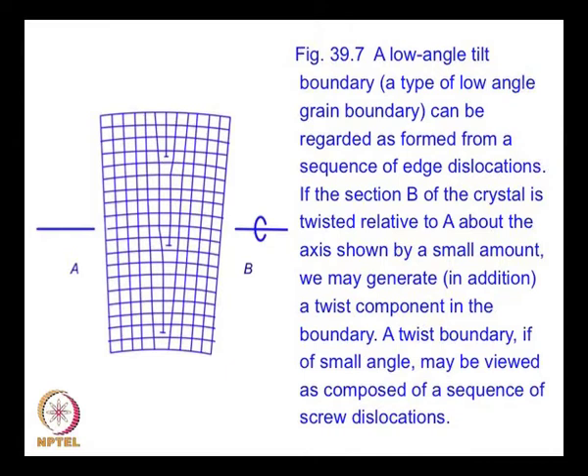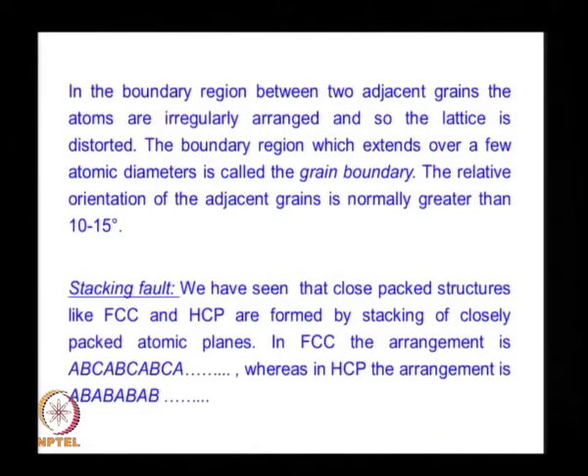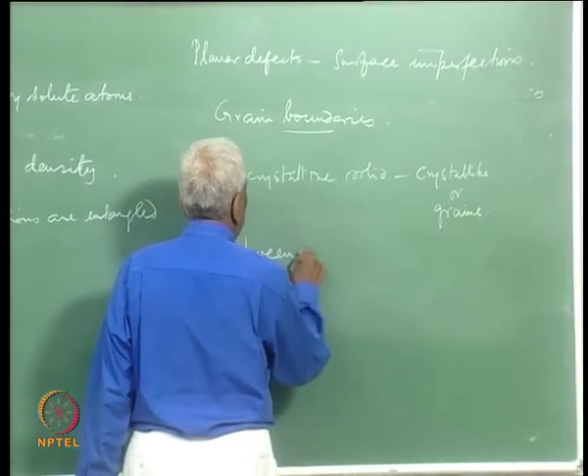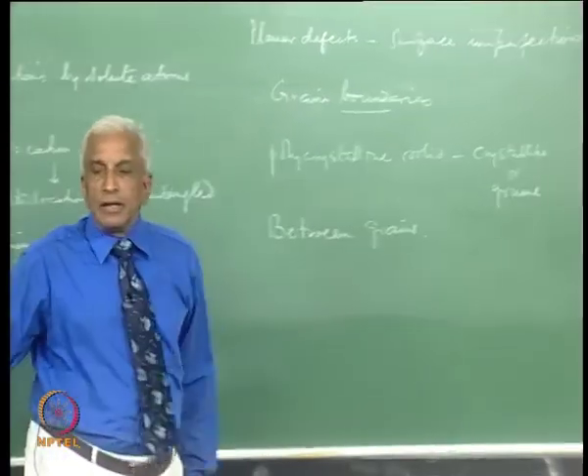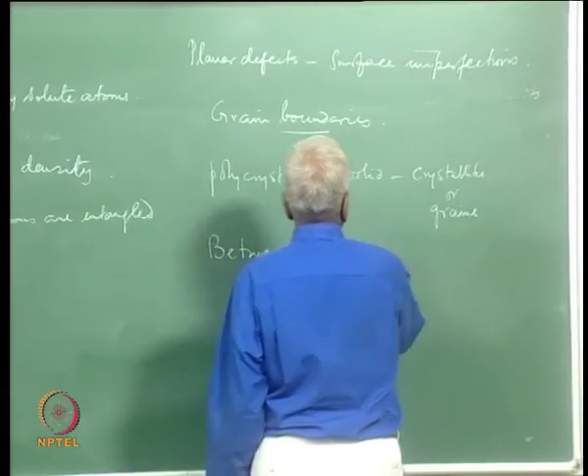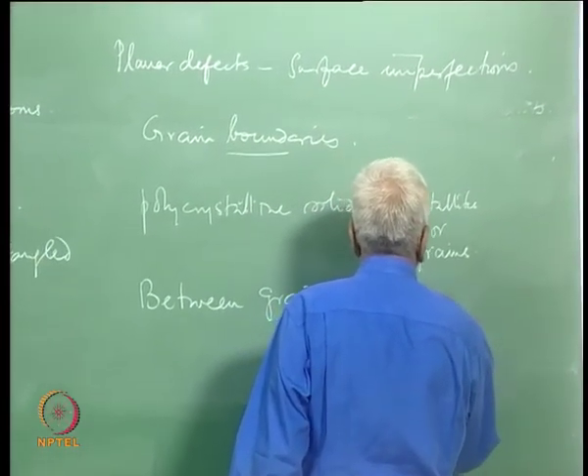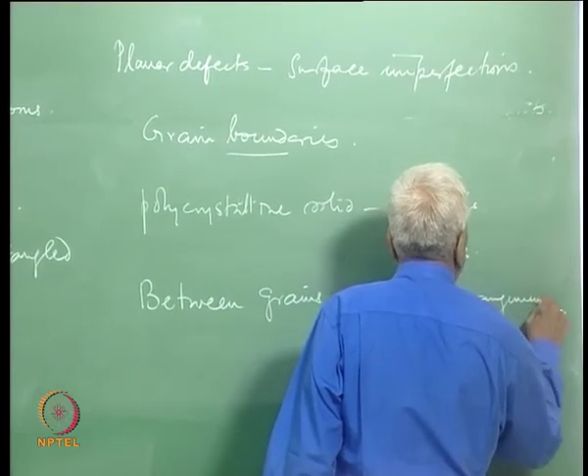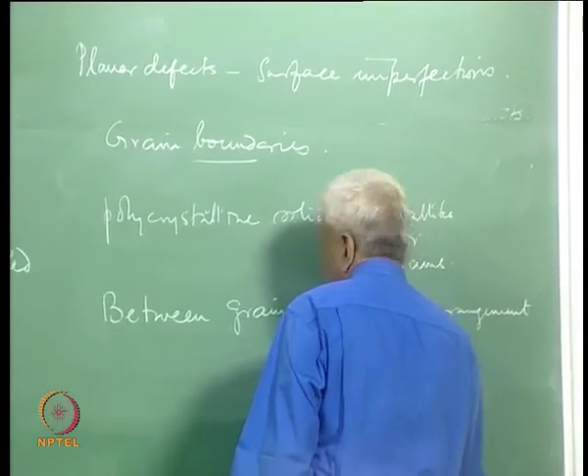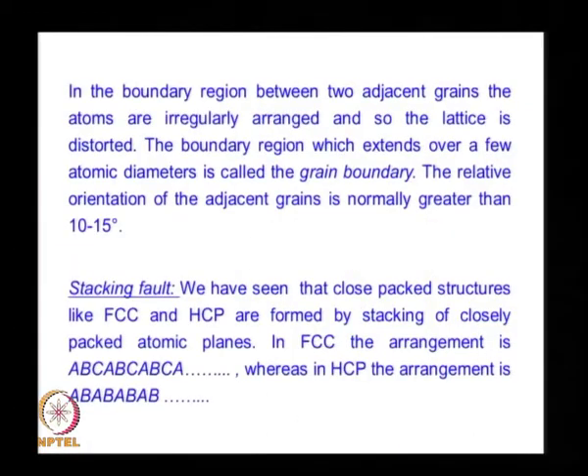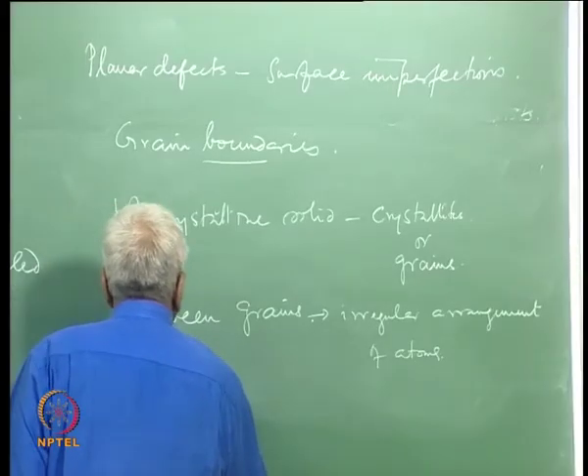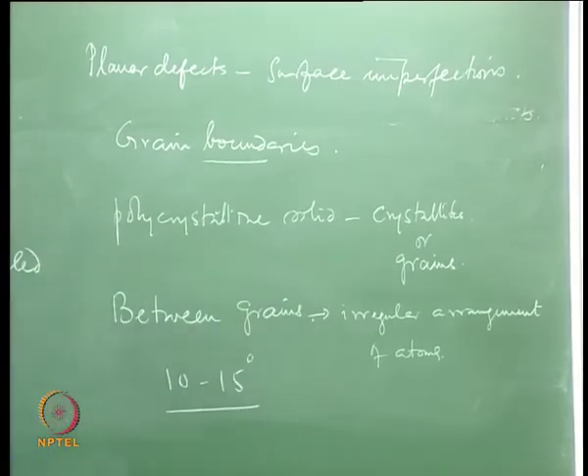which can be regarded as formed from a sequence of edge dislocations. So, you have a large number of edge dislocations as well as screw dislocations in the boundary region between two adjacent grains. That is known as the grain boundary. So, the atoms are irregularly arranged, as can be seen from this figure. The relative orientation of the different grains is usually of the order of 10 to 15 degrees, the angle between the different grains.